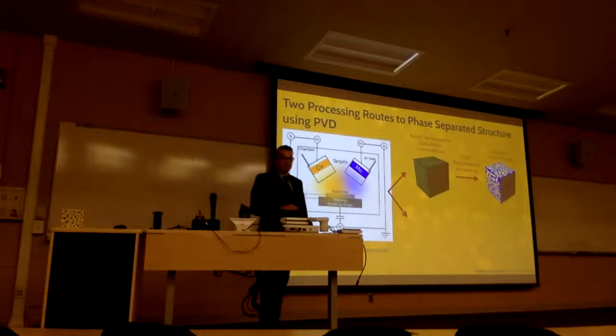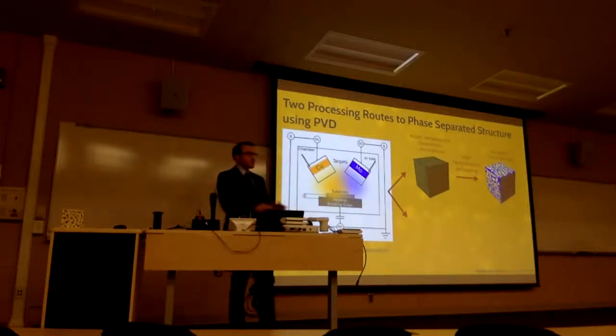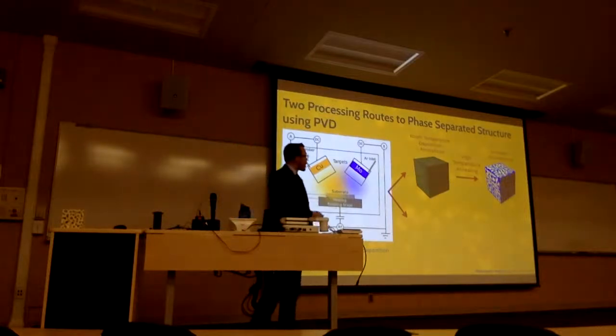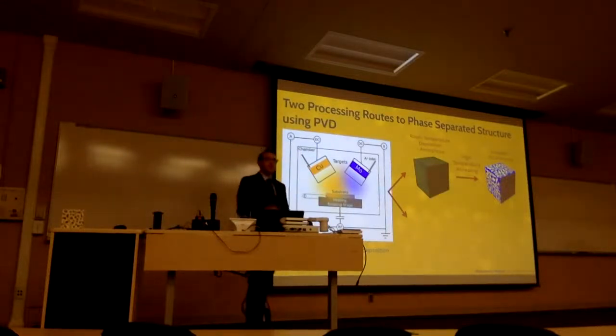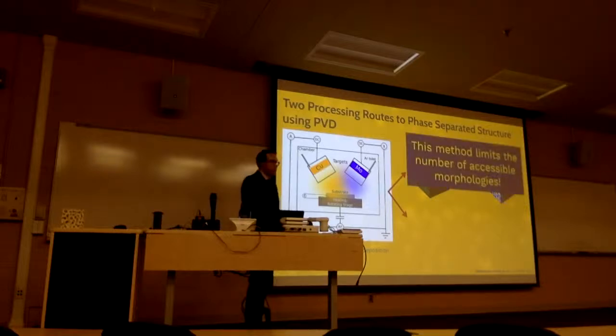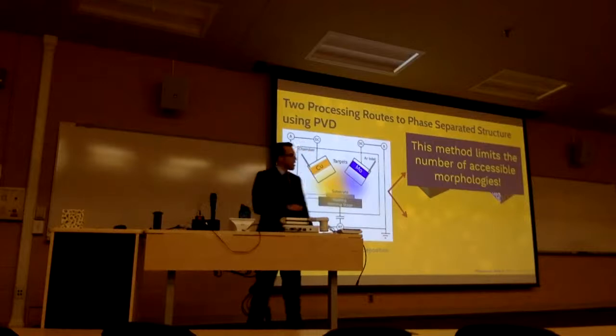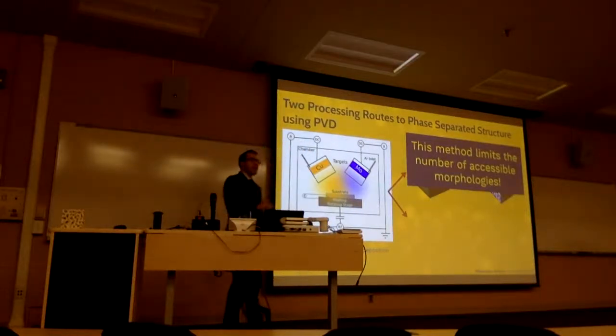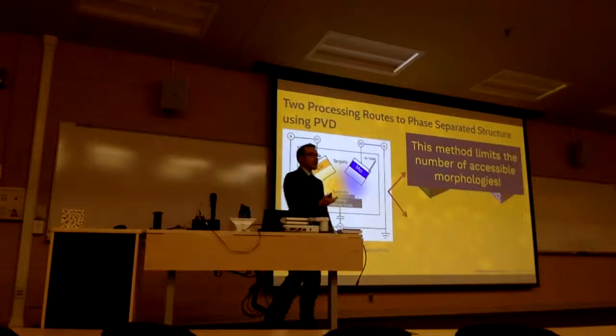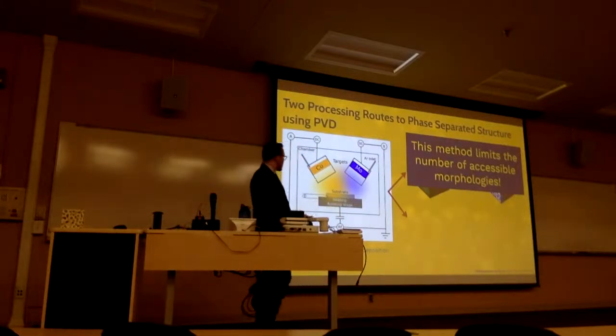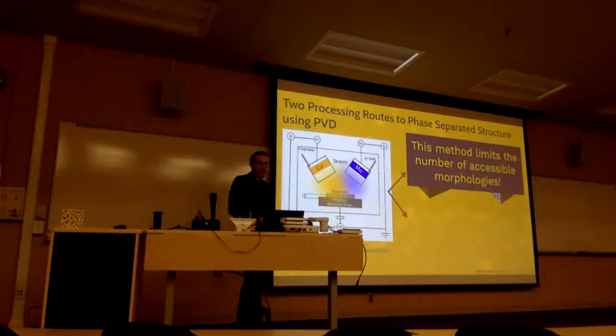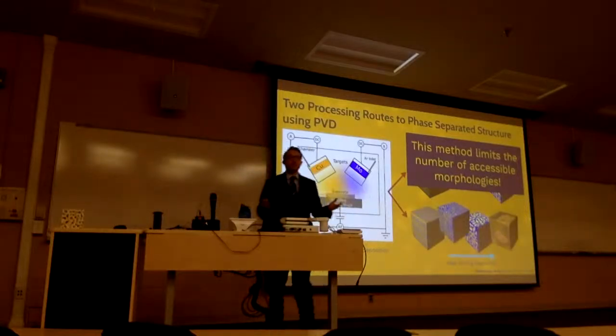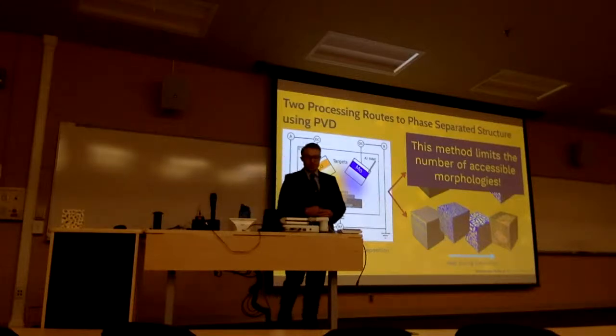Why don't we just copy that processing route? Well, the problem is that it's kind of cumbersome. We have to take the alloy out of the chamber, we have to heat it up, and the resultant morphology is actually the same every time we do it. So we're actually limited in the number of morphologies that we can achieve using that processing route. So we thought, well, why don't we change it up? We can actually add energy during deposition by heating the substrate. So why don't we add temperature while we're depositing the material? So we thought that in that case, we might be able to expand the number of morphologies that we could deposit using this processing route.